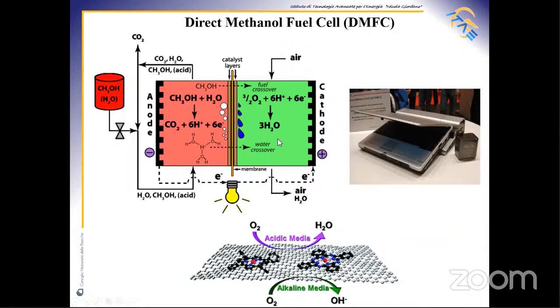The electrocatalysis of the oxygen reduction reaction is one of the limiting steps due to the slow kinetics. This requires the use of expensive platinum-based catalysts characterized by suitable activity. Moreover, one of the main drawbacks in DMFC is the methanol crossover from the anode to the cathode side through the membrane that results in a mixed potential at the cathode. Methanol permeation produces this mixed potential and reduces the overall efficiency of the direct methanol fuel cell. Platinum-free catalysts with better methanol tolerance and proper activity are considered in this talk.